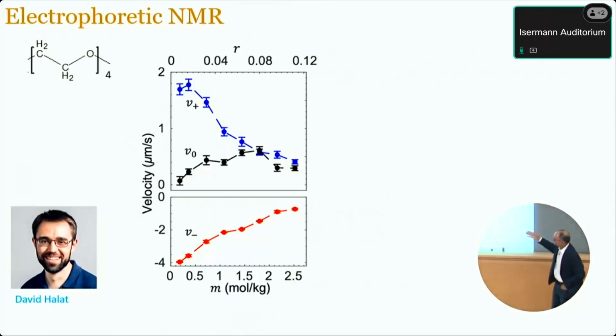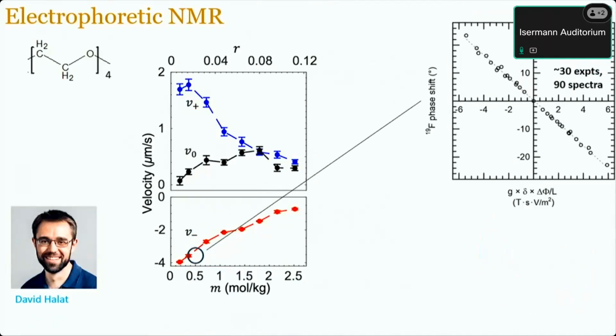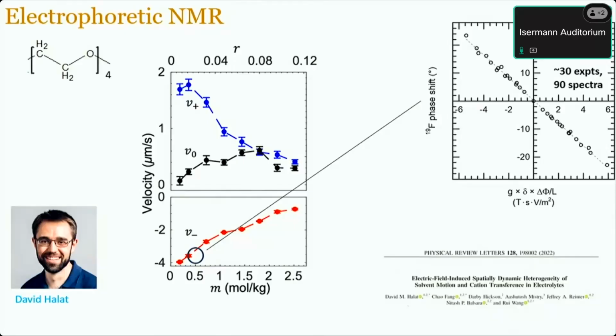This is an oligomer of 4 ethylene oxides, and we measured the 3 different velocities as a function of molality. And these are not trivial measurements. Each of those data points is based on several NMR measurements. And then in this paper, we finally use these measurements to get the transference number. And the cleanest definition of the transference number is that if you get the field-induced initial velocities, it is just this ratio. Okay.